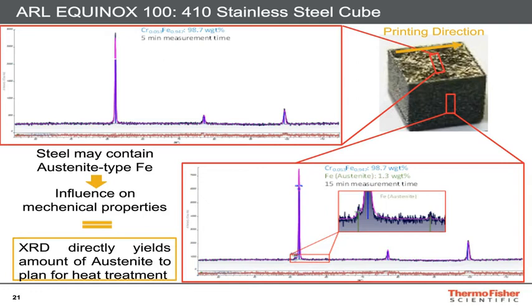In this case, we detect some anisotropy because in one direction there is no austenite, whereas in the other one there are some 1.3 weight% of austenite. So therefore, you can plan for your heat treatment process by directly analyzing your diffraction pattern.